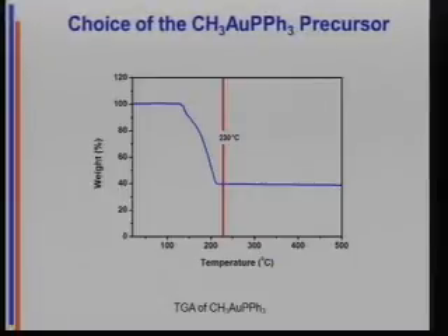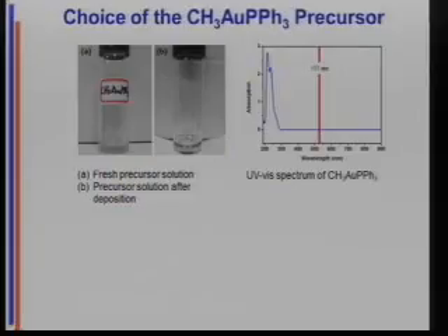And the residual mass after this decomposition corresponds to metallic gold. So I have a precursor that decomposes to metallic gold below the hotspot temperature. Okay, optical properties, well, 515 nanometers is the long pass filter. There's the UV spectrum of my compound. It looks like the UV spectrum of benzene because what I'm seeing is pi to pi star in the phenyl groups of the phosphine.